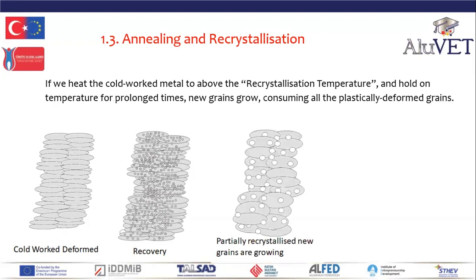As we continue to heat for longer times above the recrystallization temperature, new grains start to grow, and the grains are said to be partially recrystallized. Accompanying the partial recrystallization, we experience a reduction in tensile strength and a corresponding increase in ductility. This means by controlling the amount of recrystallization, we can manipulate the amount of new grain growth and so control or set the decrease in strength and the increase in ductility.